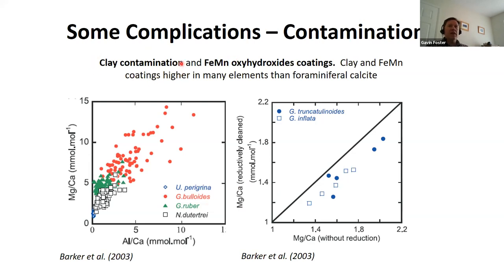They also get full of clay because they're sitting in muddy sediments, and you have to make sure that you shake off that clay using ultrasonic cleaning, again, when you're doing these bulk methods. Because as you can see on here, this is an aluminium calcium ratio against the magnesium calcium ratio. Aluminium is enriched in the clay relative to the calcite, and you see this strong correlation. So when the forams are very dirty and full of clay, you get a biased magnesium calcium ratio.